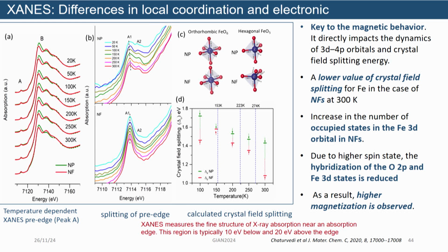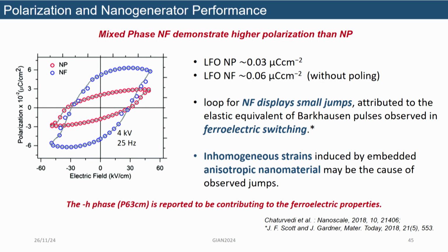So, if you see, the green one is nanoparticle and this is nanofiber. So, crystal field splitting is less in case of nanofiber, and it is more in terms of nanoparticle. This is what we calculated, and this also contributed in understanding the unusual behavior of magnetization. We again further checked the polarization, and we found that they are showing some polarization, but for nanofiber it is more impressive than nanoparticle. So, nanofibers were superior in terms of polarization.